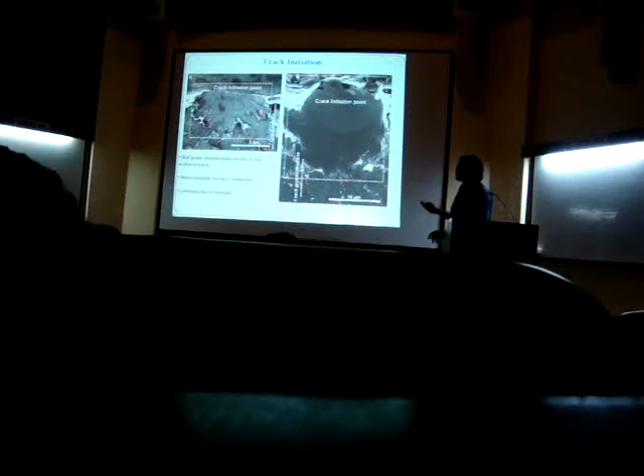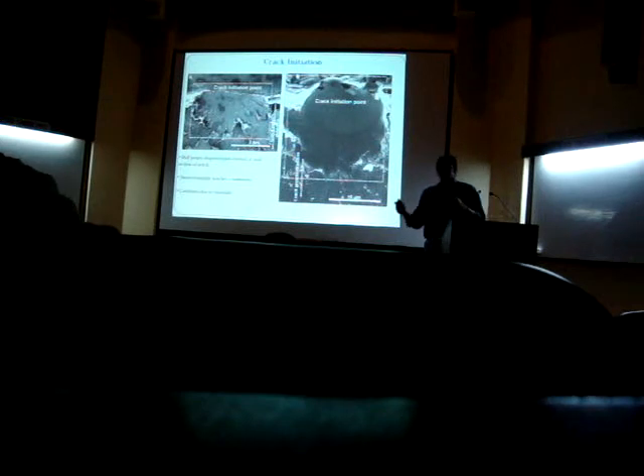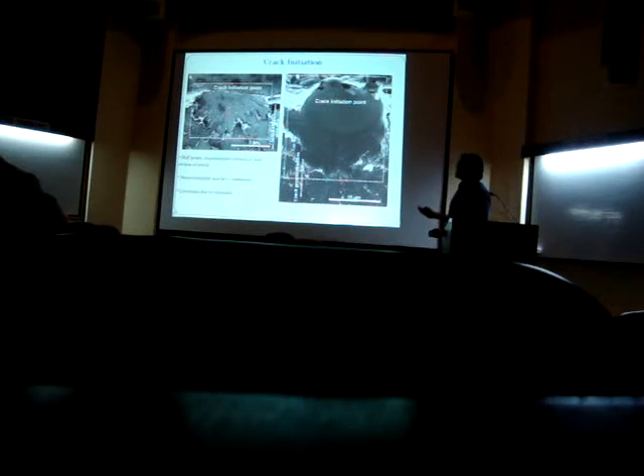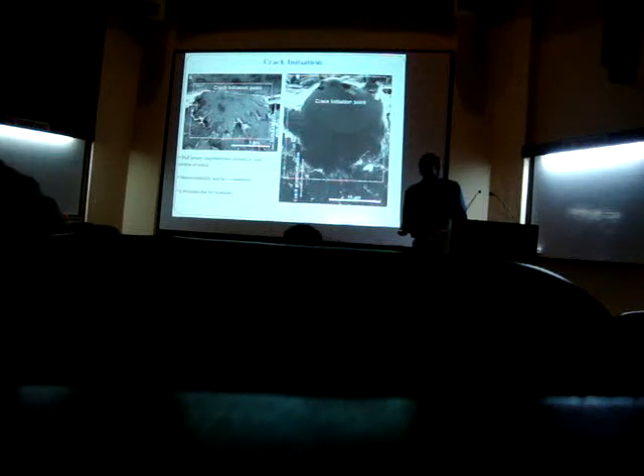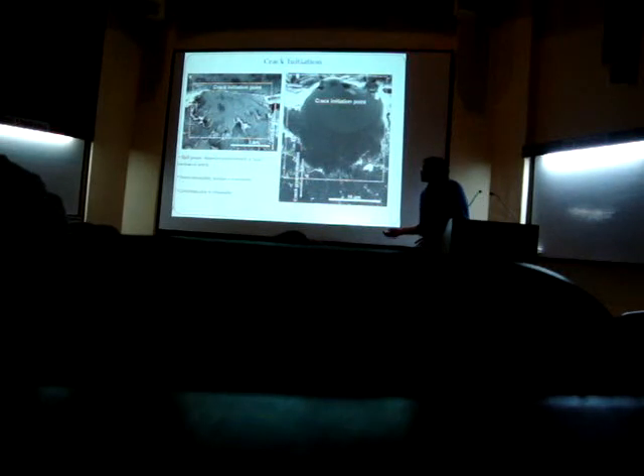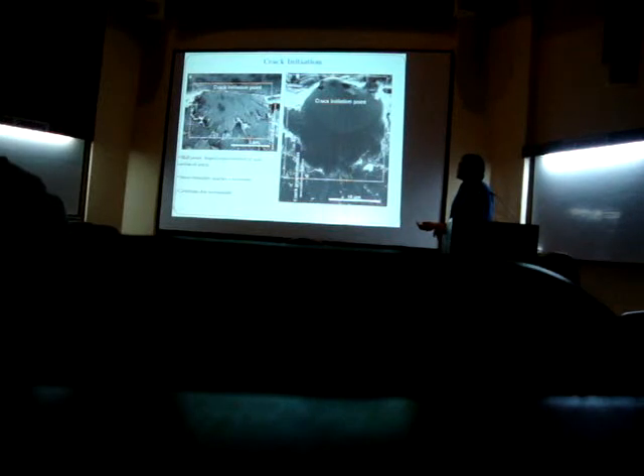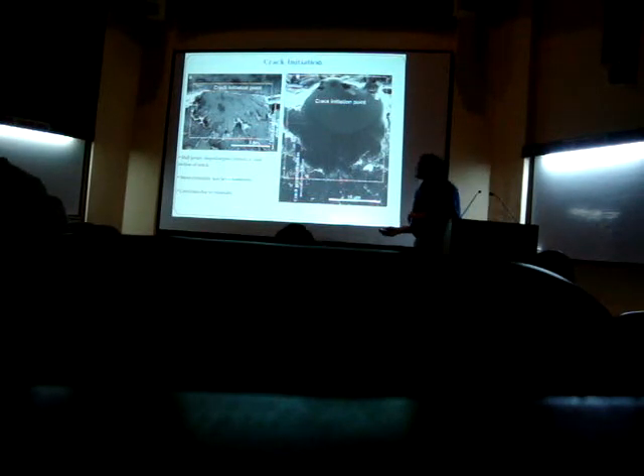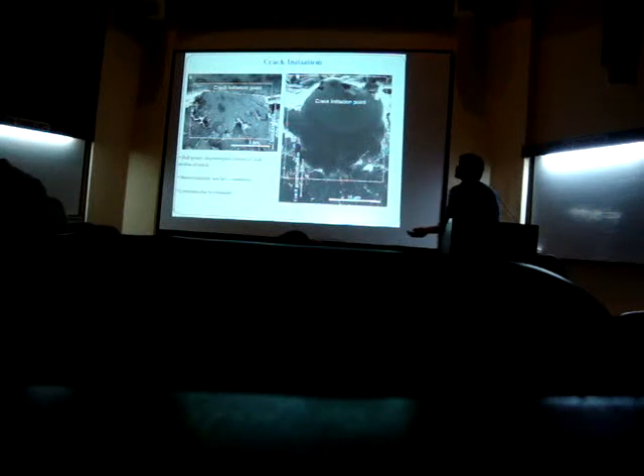So we believe that there is some kind of cavity which forms after a critical amount of stress, and this forms slightly ahead of the notch tip because of notch bending, and then it leads to the onset of crack propagation. This also indicates that in brittle BMGs, the fracture is very different from that of ductile BMGs, since it is based on a stress-based criterion. I haven't described ductile BMGs here, but I'll come back to that in the question and answer session. Now, this occurs in the center of the notch because of the large amount of triaxiality which exists.